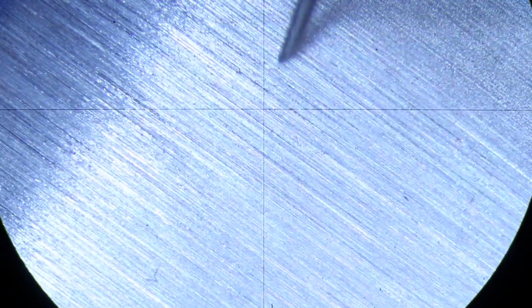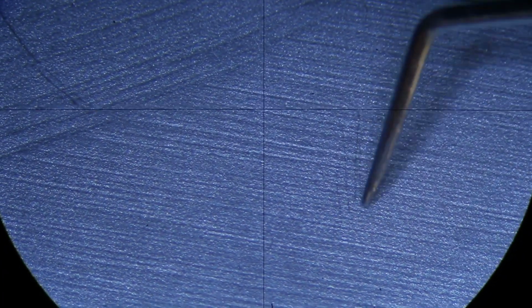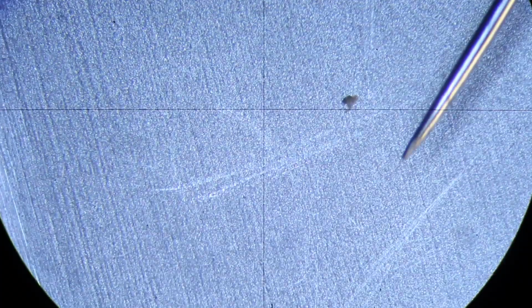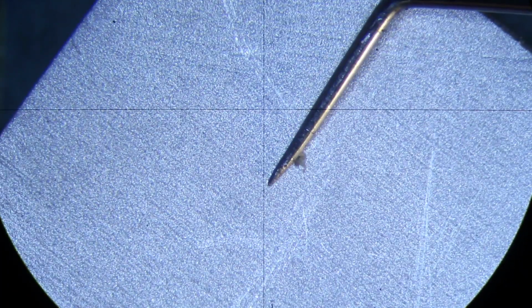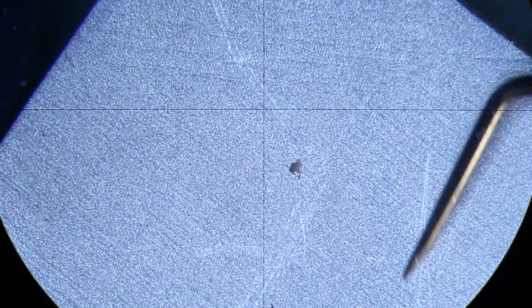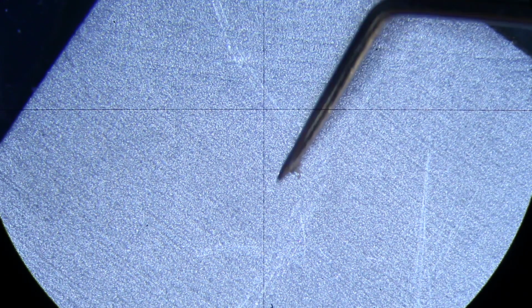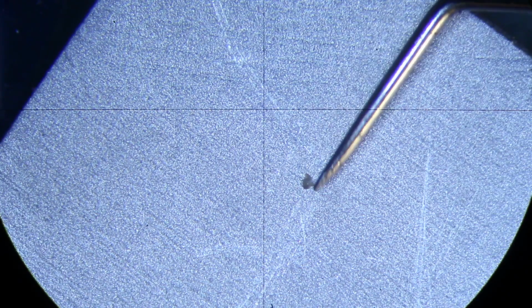And lastly, the aluminium belt sander finish down here, 240 grit. Up here, blasted. This does not get rid of the grinding marks of the belt sander. These are too large. You would have to blast this for considerable time, preferably crosswise to the lay of the grind, and at a flat angle, so you get more. I found that you get more of an abrasive effect if you go flatter against the surface you're blasting.